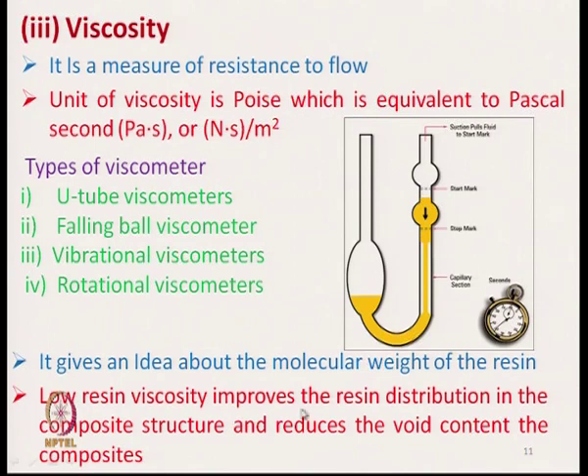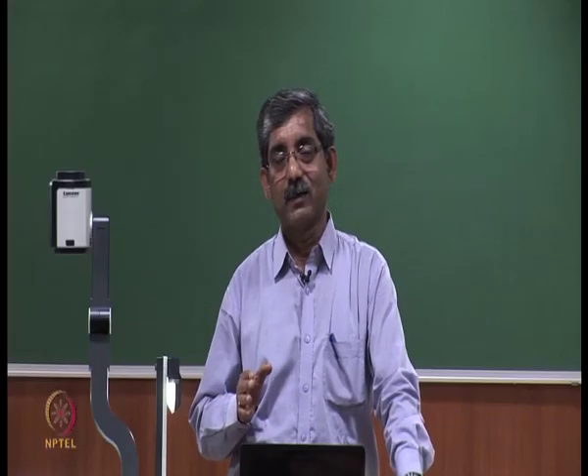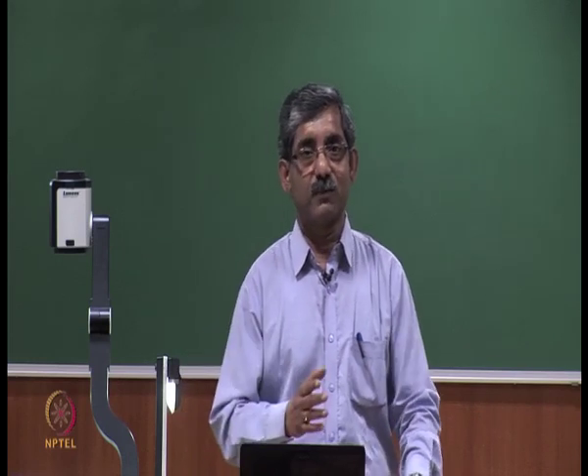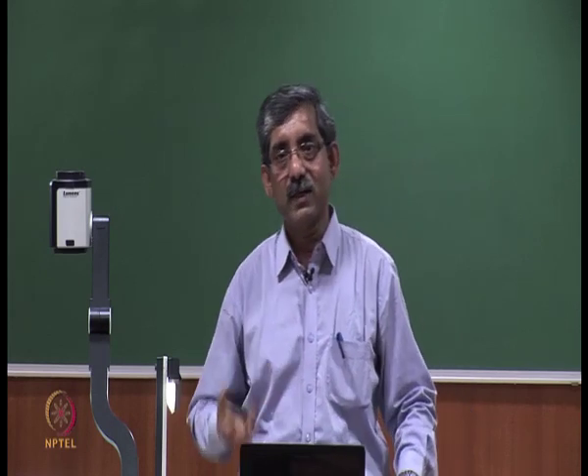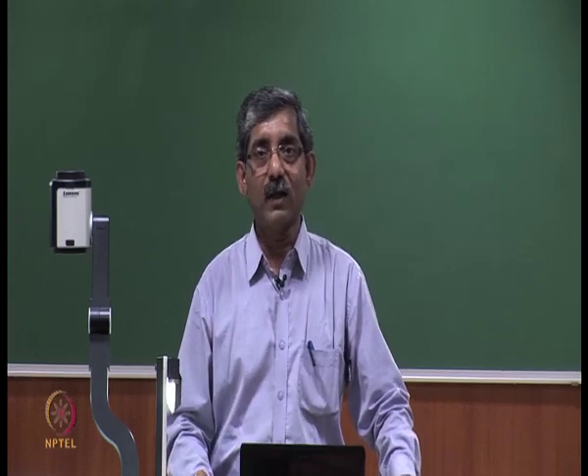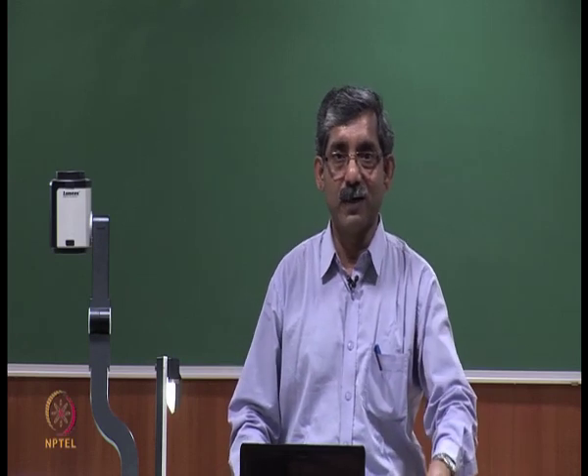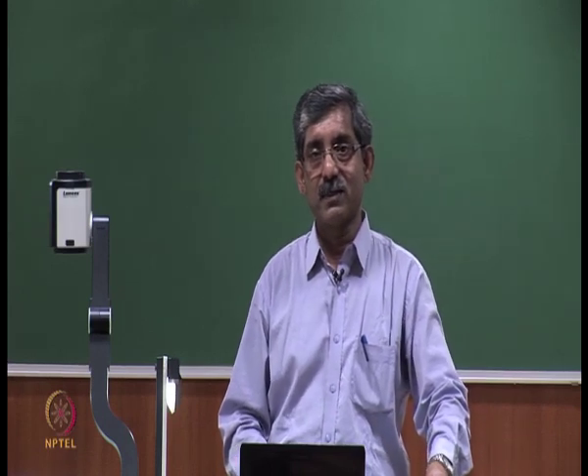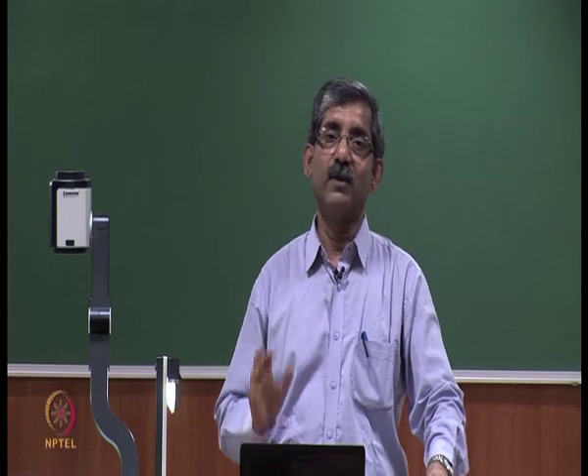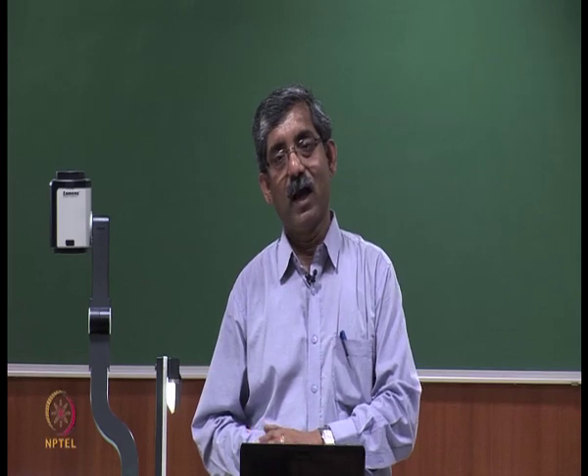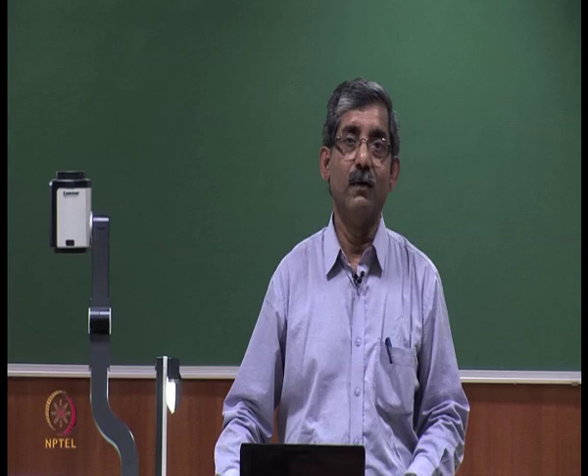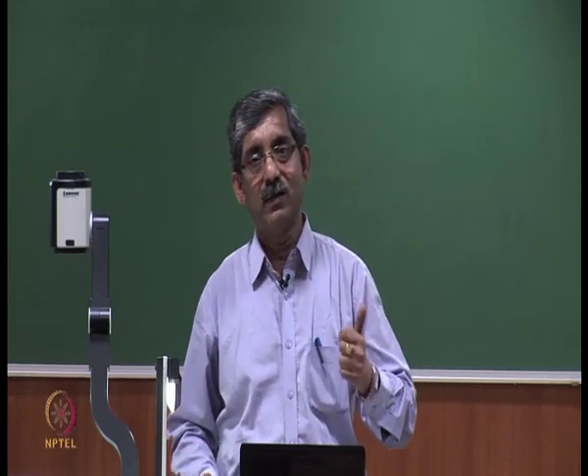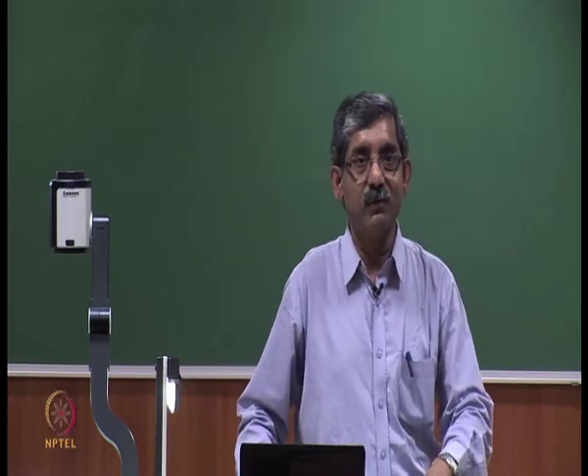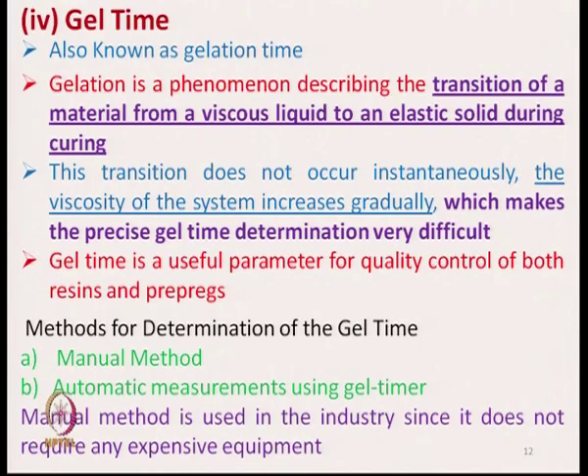Low resin viscosity improves the resin distribution in the composite structure and reduces the void content in the composite, as I have already mentioned. So, low viscosity will result in very smooth flow of matrix material within the structure and lower void content. On the other hand, if we have a matrix material with very high viscosity, we need very high pressure to penetrate this resin within the structure, and that sometimes results in void generation inside the composite, which in turn reduces the strength and other characteristics of the composite.